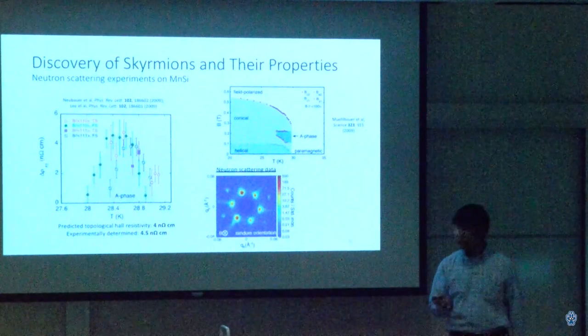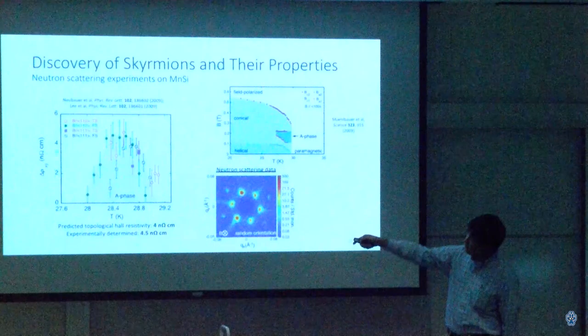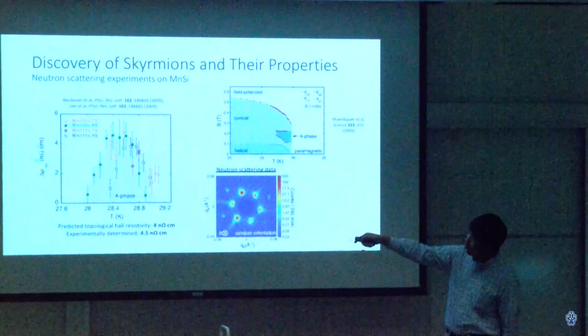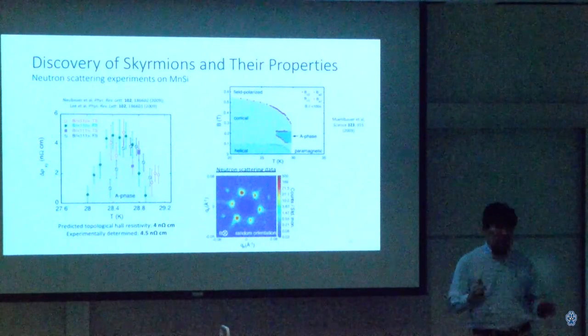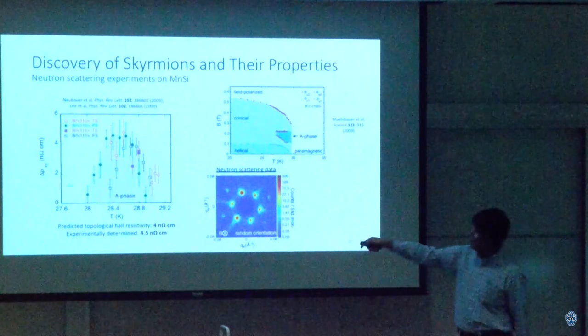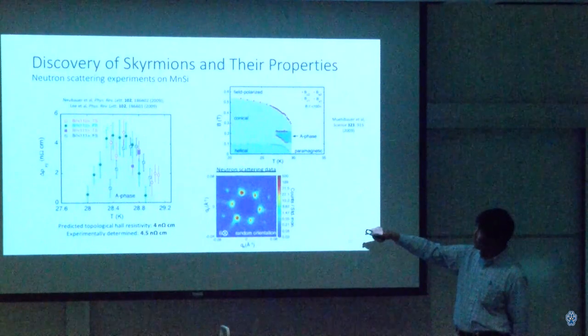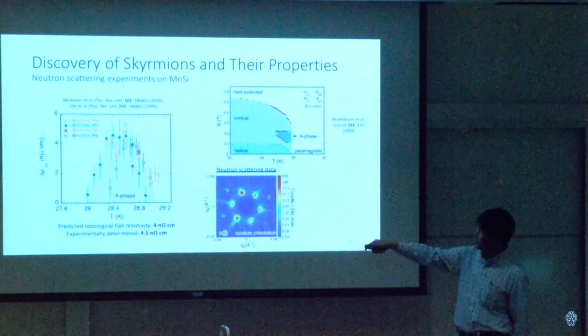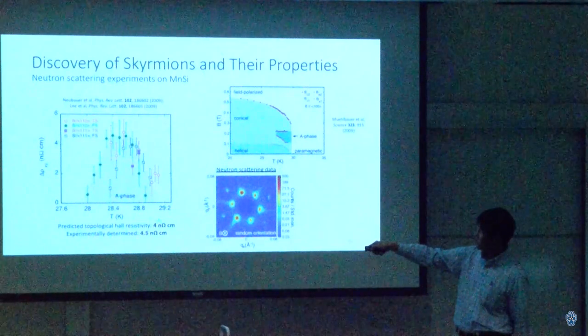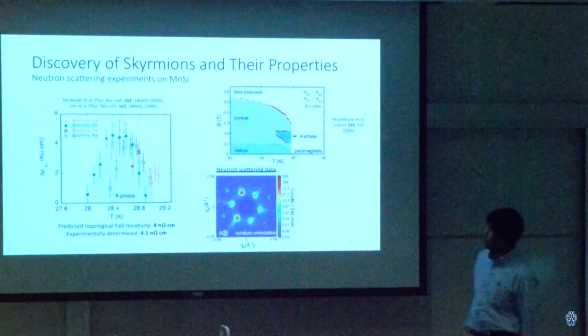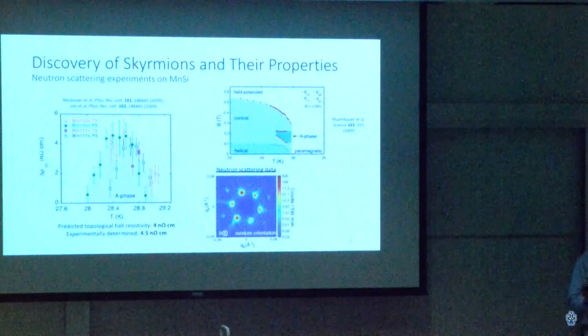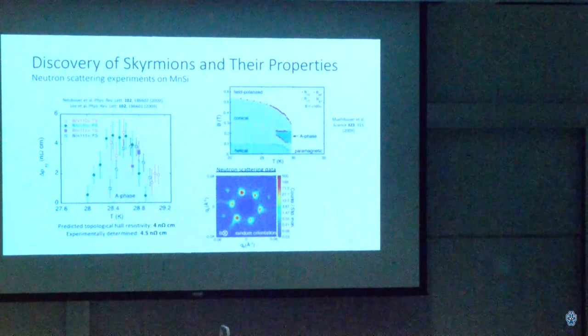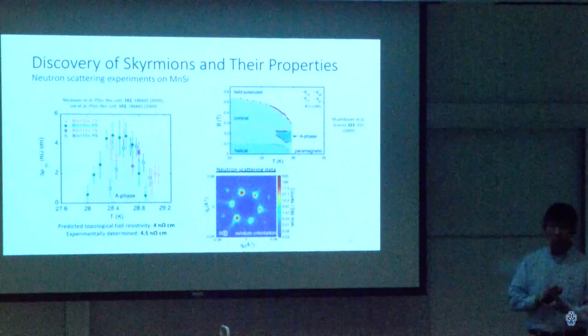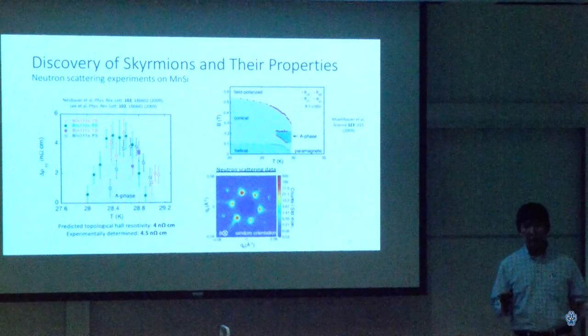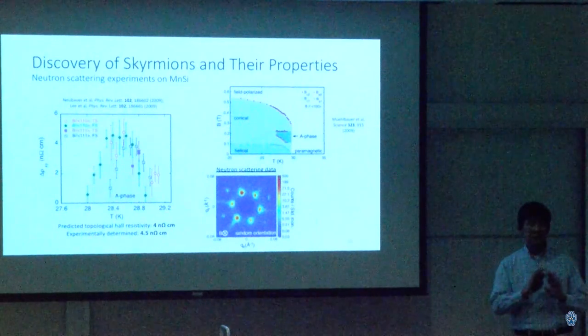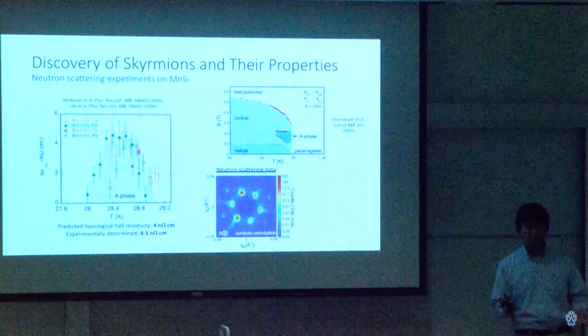It's a very small effect. The Hall resistivity is measured in nano-ohm centimeters. That's a very small unit indeed. And for having a very sensitive measurement with large error bars, you can see that the predicted Hall resistivity came really darn close to the measured resistivity, 10% or so. Not bad for a sensitive measurement. So in 2009, all this work occurred, and suddenly a new field, the field of skyrmion science, was born.